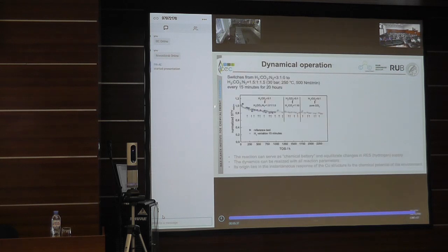The next one is now high pressure dynamical operation. You have a first indication that the zinc oxide and copper system is dynamical with each other under operation conditions. And the question is, do we see this also in high pressure performance? And the answer is yes, because this is a reaction that you can squeeze with reaction parameters however you like, and the performance is always the same.